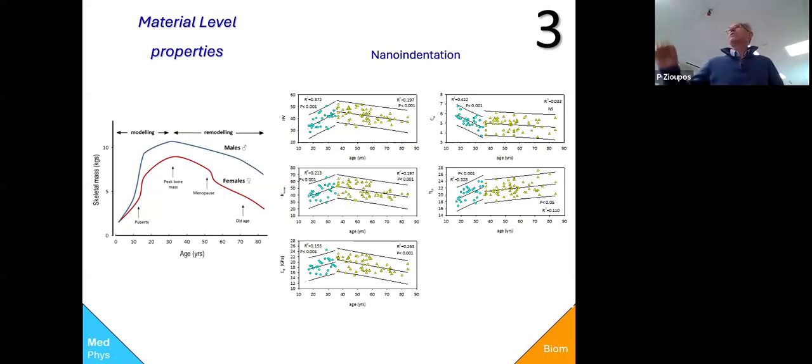What is it? So what we did is, I got tissue from 88 cadavers, from 17 to 88 years old, and we took sections from clavicles and ribs, and we did a number of studies on the bone material itself. Blind studies, regardless of age. Let's see what the tissue gives us. And this is the nanoindentation data. And there was a precise point at 35 where something changed in the biology of the human being. This is one ethnic group.